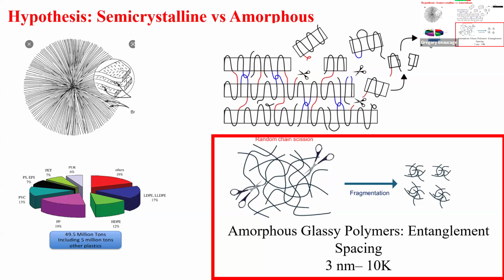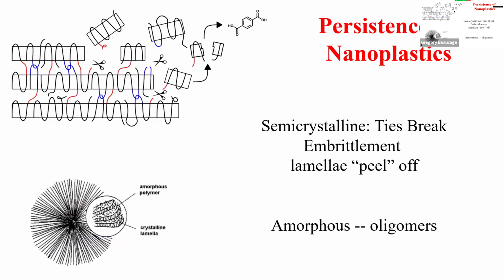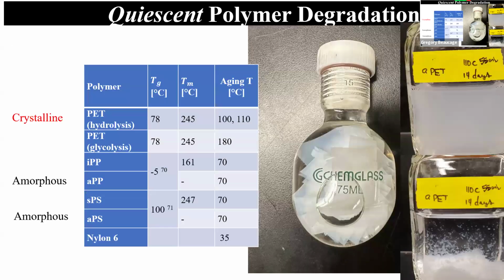Cool. So this is a long introduction. Let's actually do some experiment. This is sort of the story I have. Everybody got that? So we've done now, I think, something of the order of 8 or 10 polymers. We do these pairs. For example, isotactic polypropylene, atactic polypropylene. Same chemistry, right? One has an amorphous structure, no structure at all. This is a semicrystalline structure with lamellae. And the argument I'm making is that the isotactic should make nanoplastic, the amorphous one should not. That's generally the point. Polyethylene terephthalate that I'm going to make is about 20% crystalline. There are a few others. There's polystyrene, two versions, and nylon is semicrystalline.